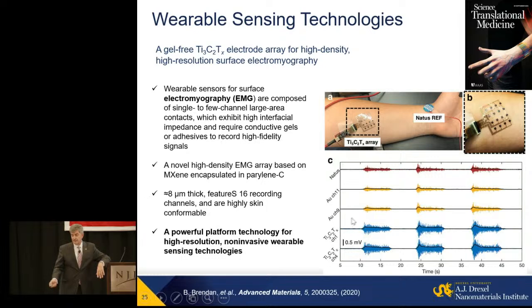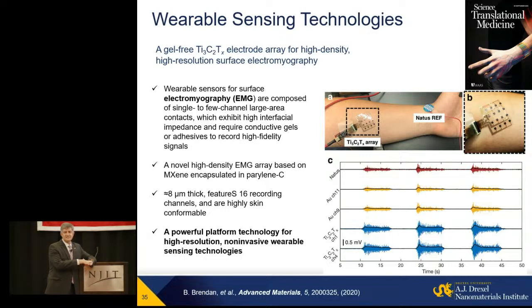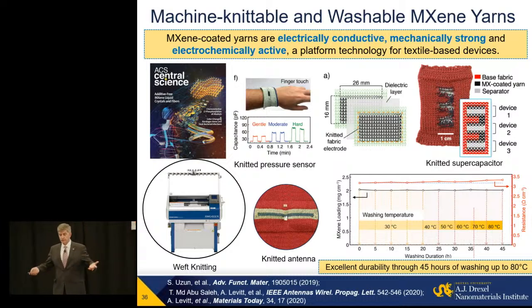Titanium carbide MXene gives you much higher sensitivity. You see this type of spikes compared to commercial gold sensors and lab-made gold sensors. Not because it's more conducting than gold. It simply has lower impedance with skin. As a result, you get higher sensitivity. And it can be made of titanium carbide, which will be much cheaper here. Of course, you can embed it in textiles somewhere else here.